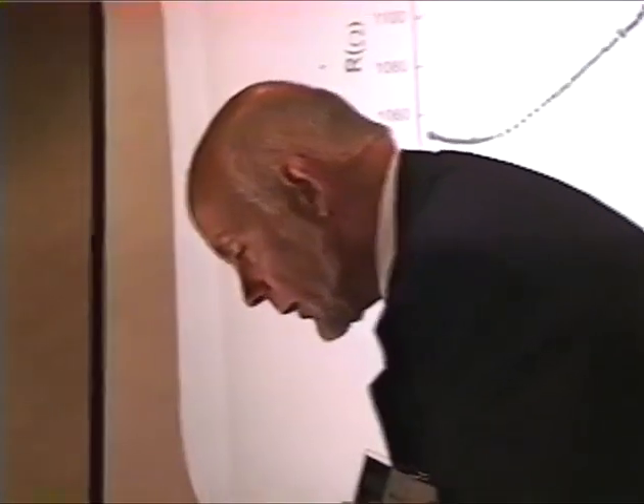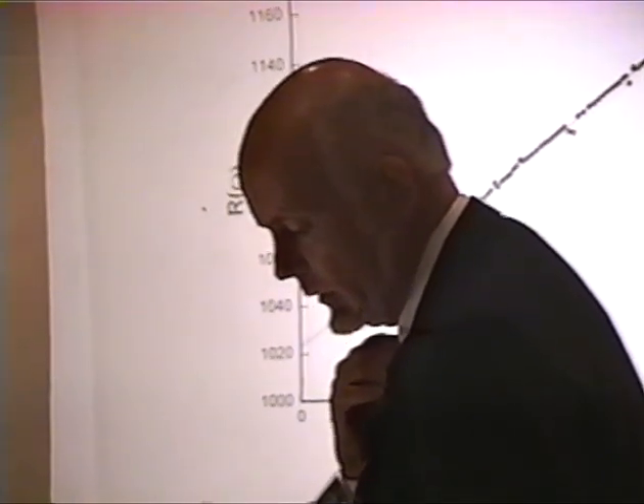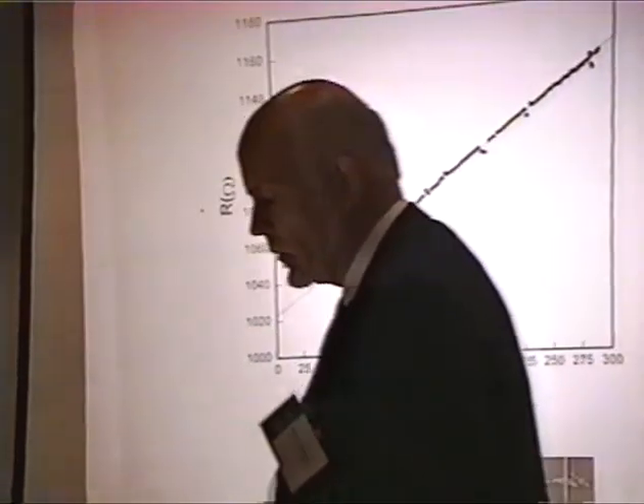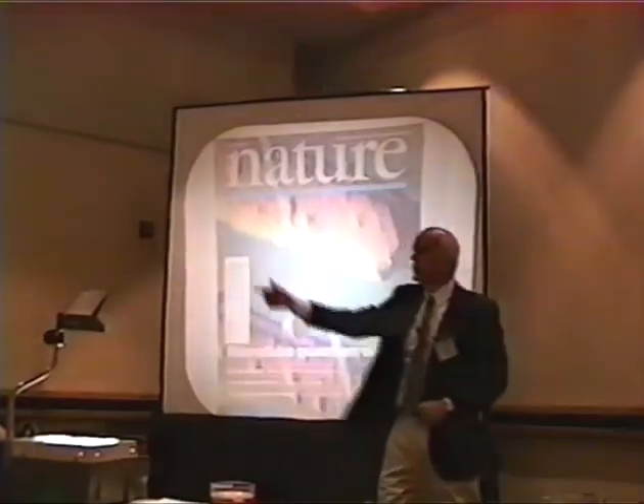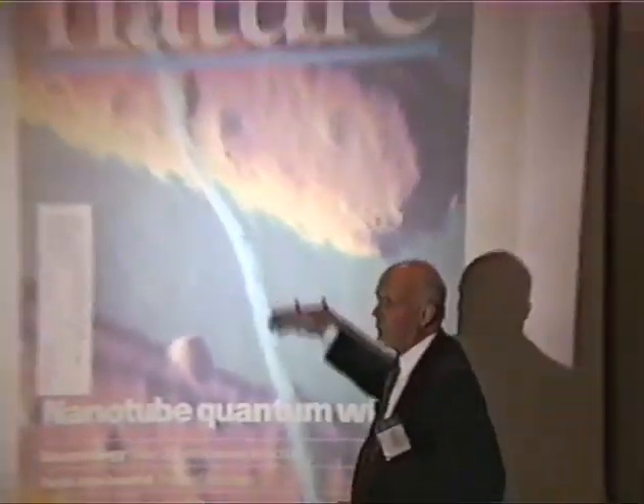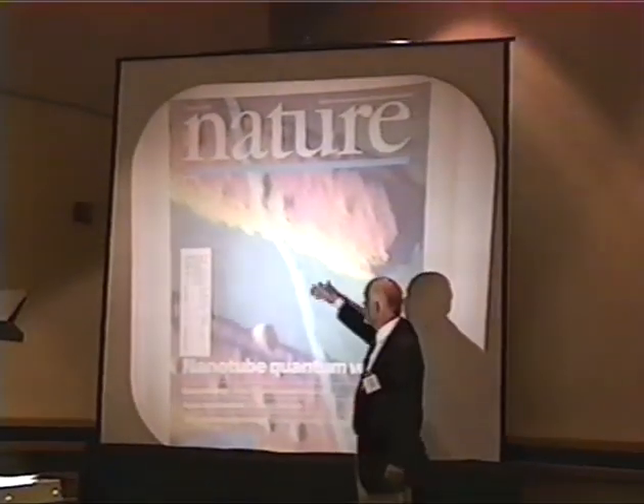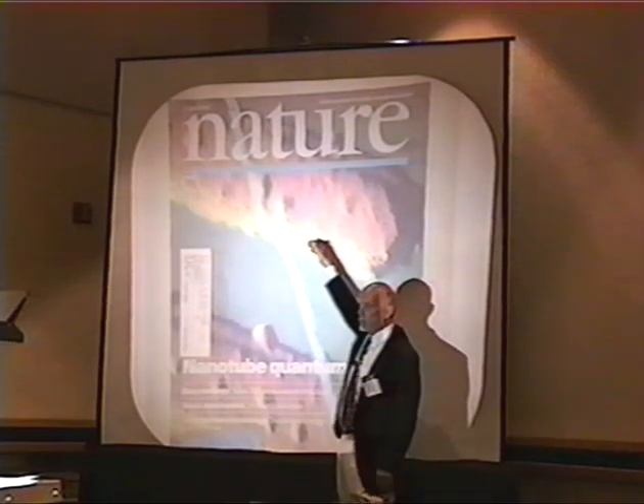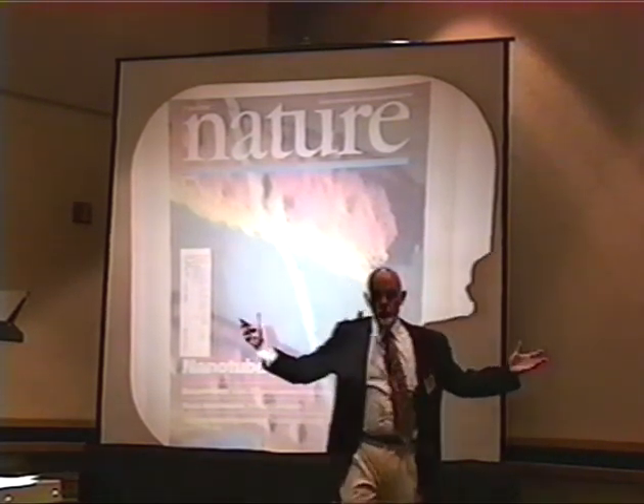There have been some beautiful experiments done recently in Holland and in California and Berkeley on quantum transport of individual ones. One of these done by Cees Dekker and his crew. Cees is here in the audience someplace. Cees is over here, on the cover of Nature, which very nicely showed that the transport along this wire involves coherent states that appear to be coherent over the whole length of this molecular wire, actually for distances considerably longer than you see here, on the order of 3 microns in length.